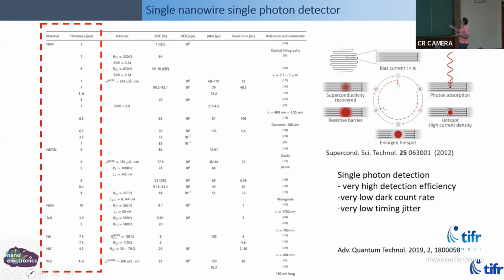So let me explain, for pedagogy, how this works. You have a long winding wire of a superconductor, and then a photon falls on it, and it locally dumps heat into the system. It creates a hot spot. When the current goes through, it basically has a feedback mechanism, so it enlarges the spot further. Locally, the superconductor goes into a normal state. And if you were monitoring either the resistance or some kinetic inductance of the system, which is a measure of the superconductivity, you would immediately pick out this change in the local state of the system.